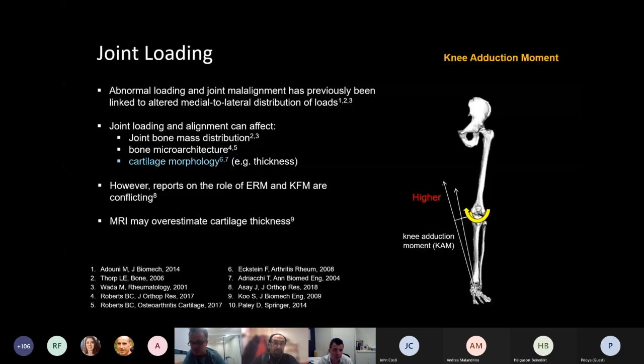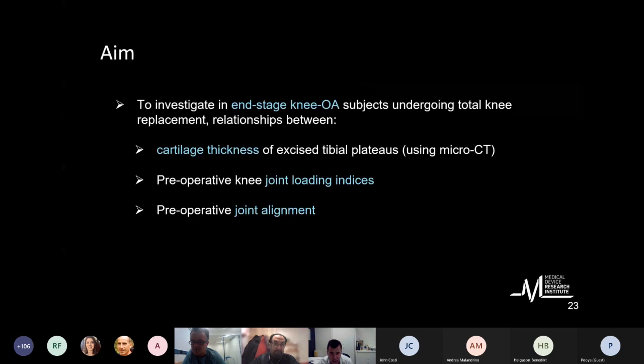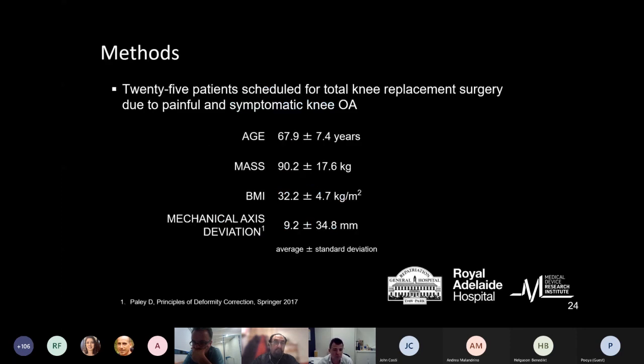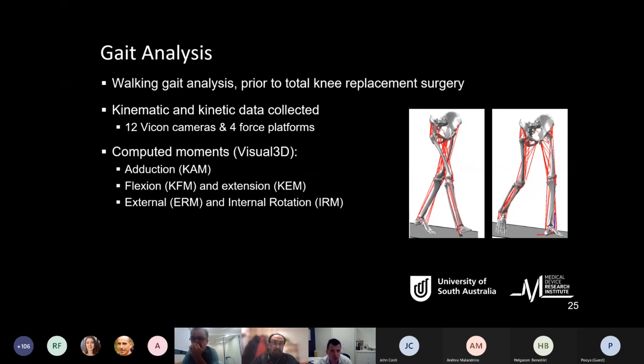And so I'm showing here the current study by Sophie, where we are looking at the cartilage thickness of excised tibial plateaus using micro-CT in end-stage knee osteoarthritis undergoing total knee replacement, and the relationship with the preoperative knee joint loading indices and joint alignment. So this is the age, about 70 years old, BMI about 32, and they were, on average, varus aligned, but slightly varus aligned, but we had a mixed group there.